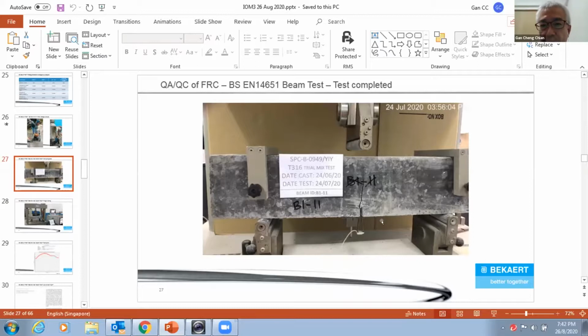Yes, we do a 2-point load if there is no notch below. That means I do not cut the beam. This beam has a cut at the center. Tim, if you look here, it has a cut at the center. So because there is a cut at the center, what I do is I just use 1 point and push it, and it will crack at the exact line. Now, if I don't cut the beam, then I'm going to use a 2-point testing. All right. So that you get the flexural strength. Yeah, so that I will get the flexural.